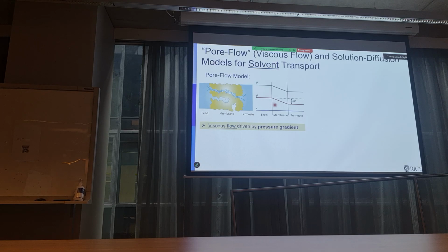So if this is the pressure gradient and there's no change in chemistry, of course the chemical potential is determined by the pressure gradient. And this is described by the classic Darcy's law. Although Darcy's law, as those of you who studied it in some classes know, was found empirically, now you can derive Darcy's law from the Navier-Stokes equation. You can solve the Navier-Stokes equation inside the pore, do averaging, and you can rederive the equation.